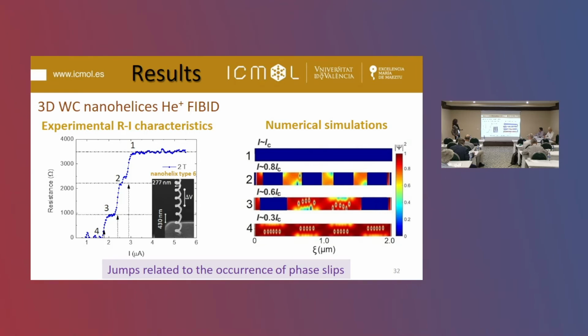At the second point, it happens in almost a similar way. Two more regions of phase slips are inserted in the wire, and we observe again a second jump in the values of the resistance. So this is a demonstration and proof that this three-dimensional geometry can tune the superconducting properties of these nanohelices, because of course this is not visible in planar strips with the same dimensions.